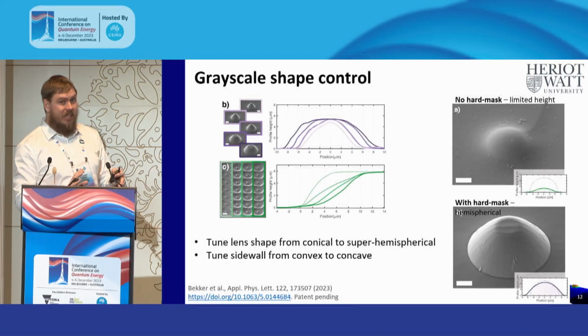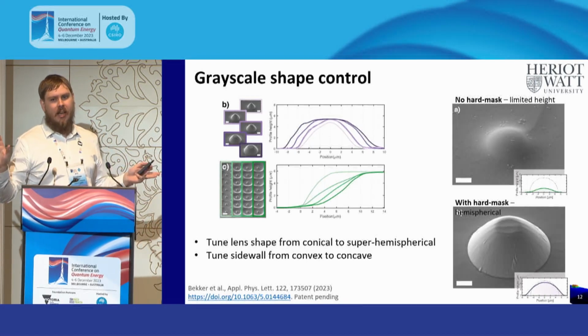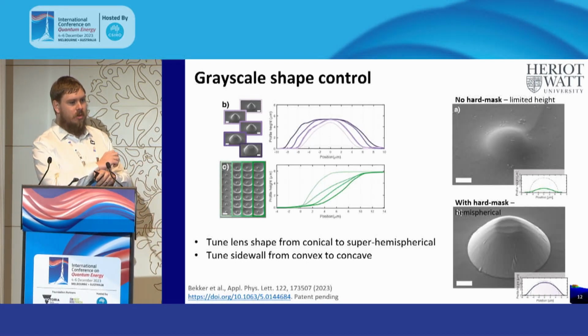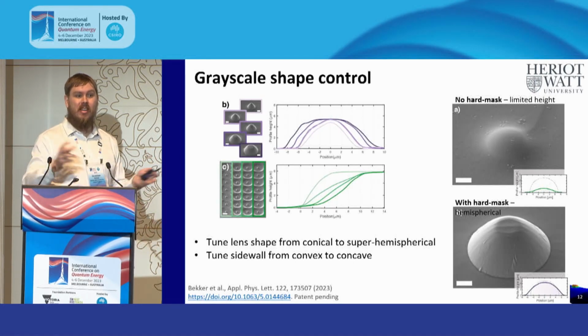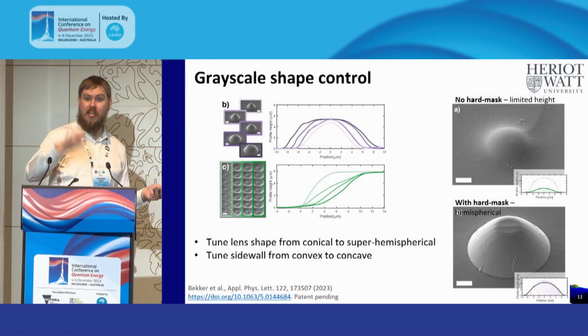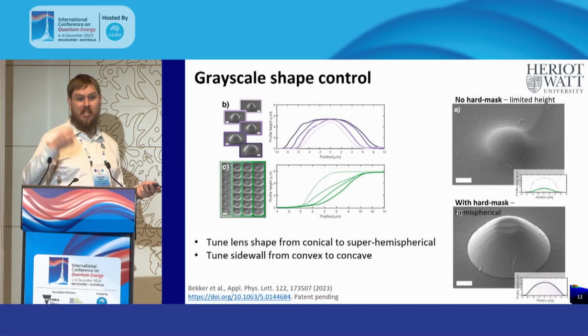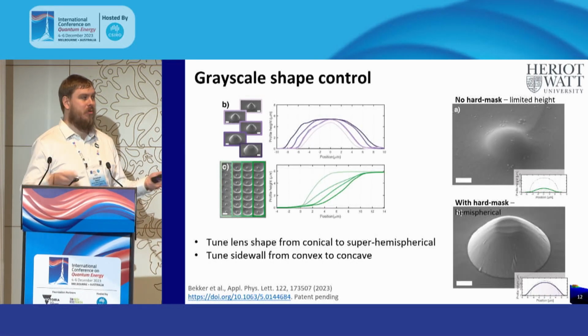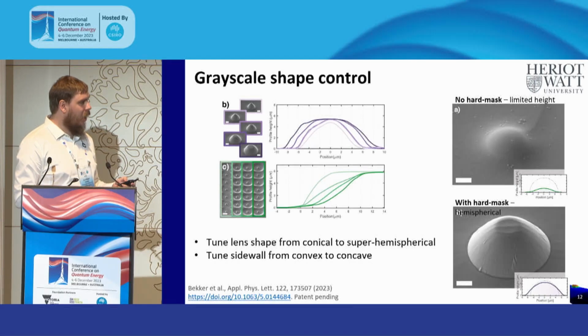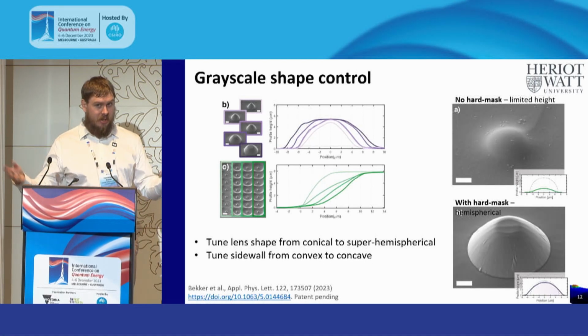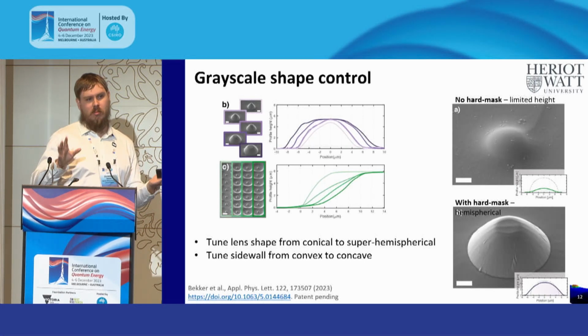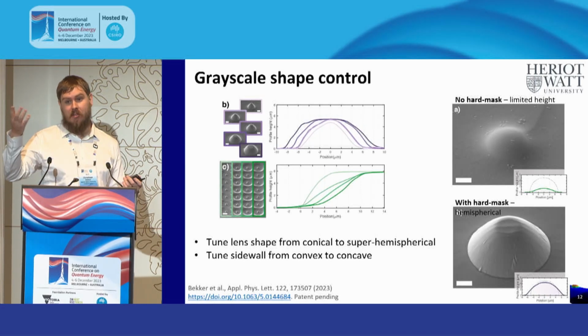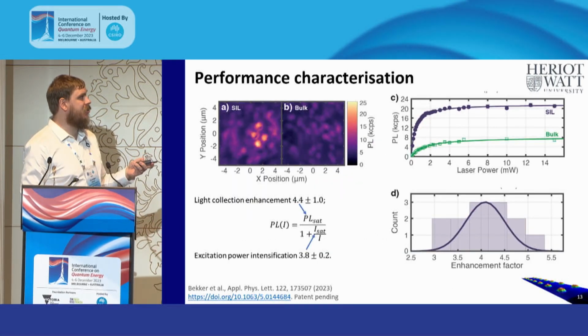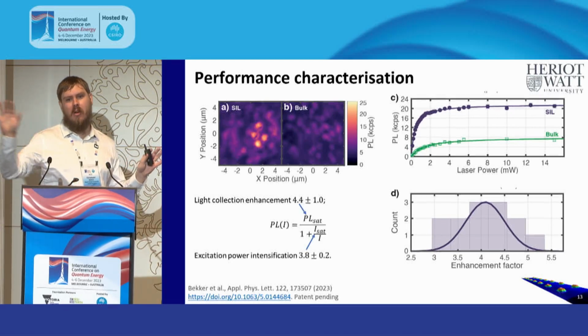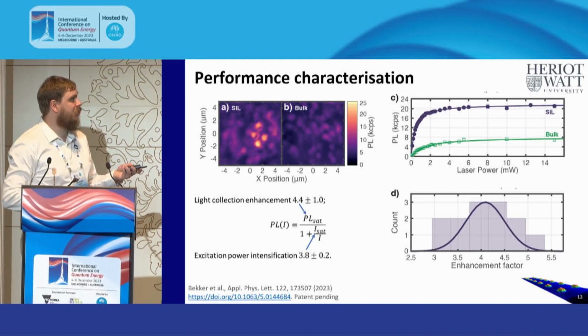So then we took these devices. We initially shot electrons at the whole chip, so shooting high energy electrons. We create individual vacancies, so we create silicon vacancies, and these are the emitters which we're studying in this particular case. These emitters, as I say, you pump them with red light, and then they emit in infrared, and so we can look at photoluminescence from these. And so on the right here, this is just in the box. It's just a reference to a little bit of the sample where we can see all these different spots.